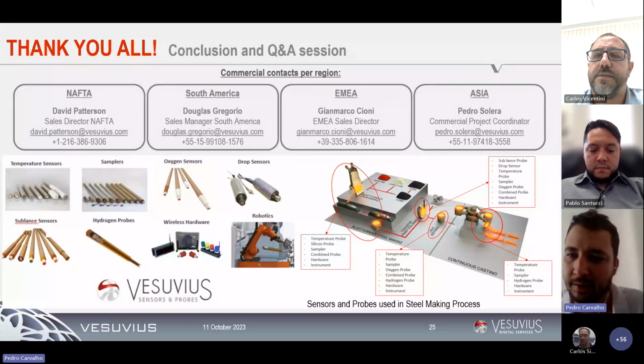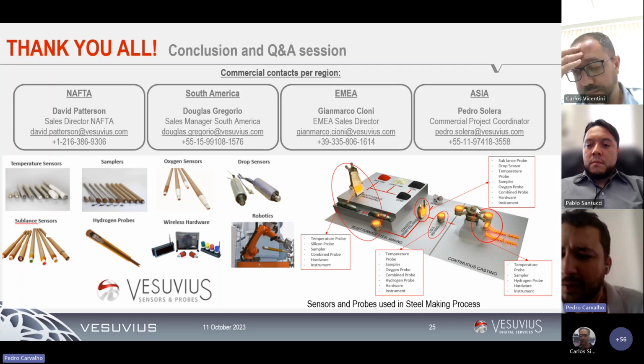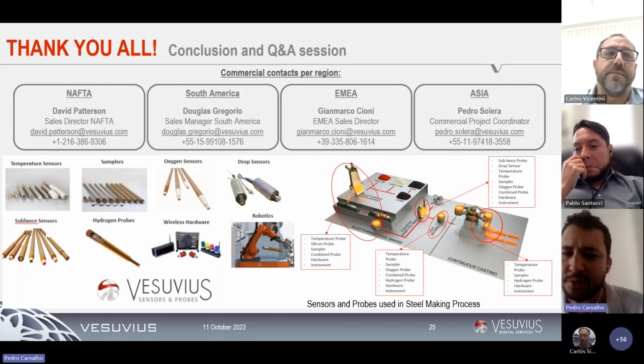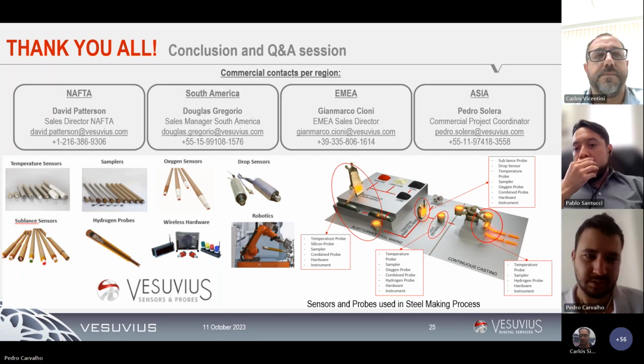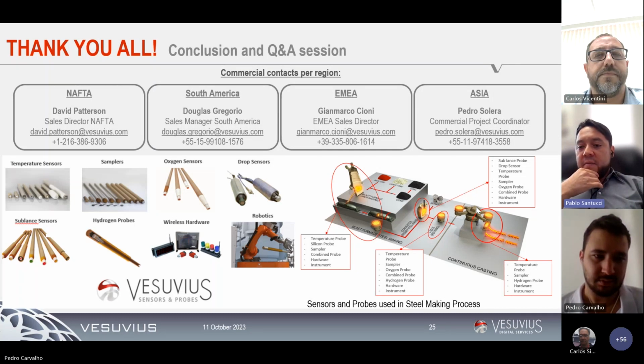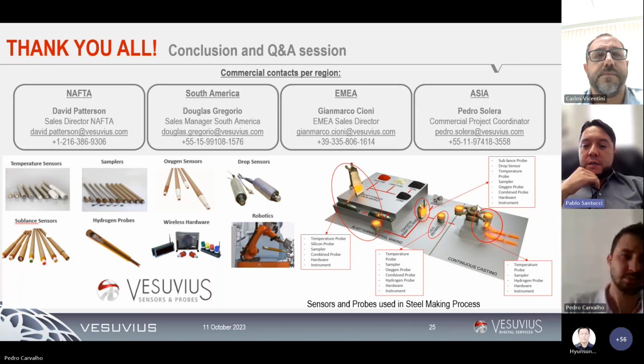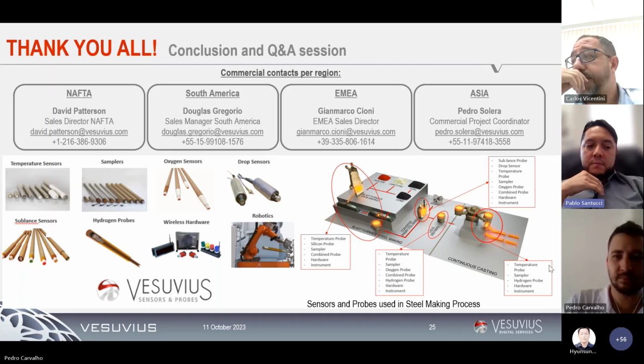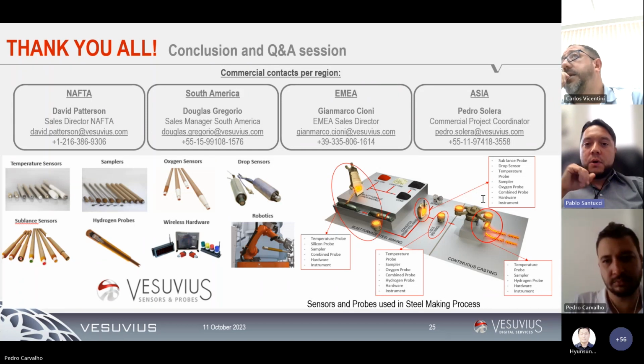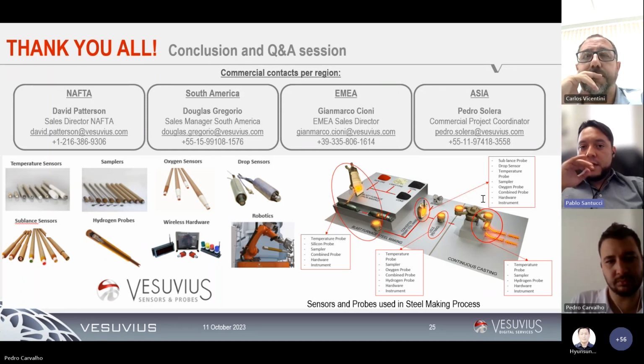Wolfram's question: what is the critical minimum hydrogen content in low alloyed steel melts measured with your device? Well, I would say the minimum range that our system can read is 0.5 ppm. So that's the very minimum range for hydrogen from our system.